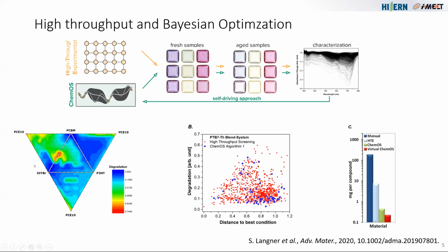What you can see here is that we can within a very short time screen a big parameter space of like 4 different components of different materials for their air stability pretty fast. And we can also do that with very little material, since we are only drop casting very small films.